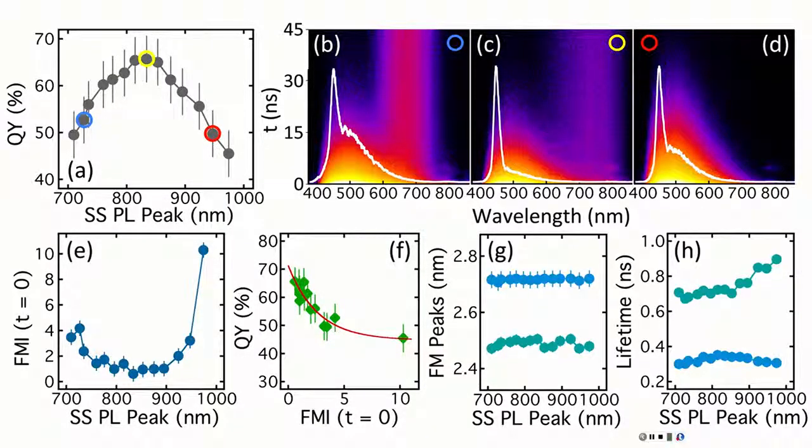But I guess if the mixing already happens at 10 nanometers, it would just be accentuated at 2 and 4, if that's how it actually happens. And you would just say that any kind of surface defect would give you this mixing. Right? They don't even invoke states associated with defects. They just say it's always mixing, and that anything will cause this mixing: quantum confinement causes it, defects cause it, poor surface passivation causes it.